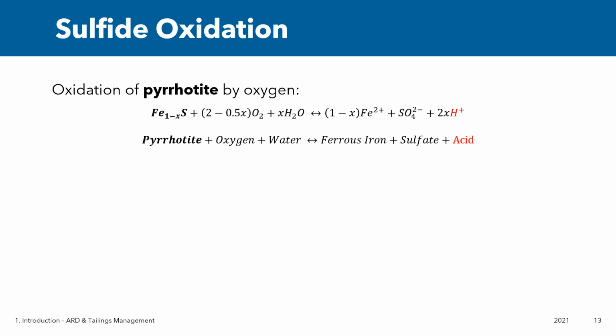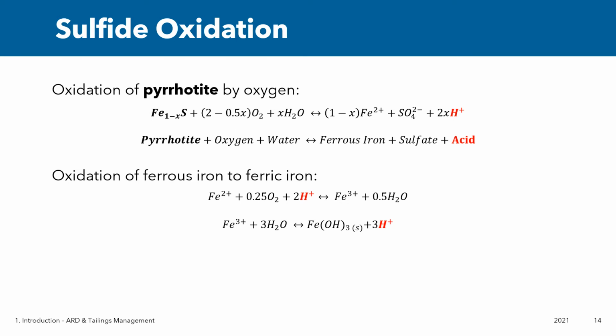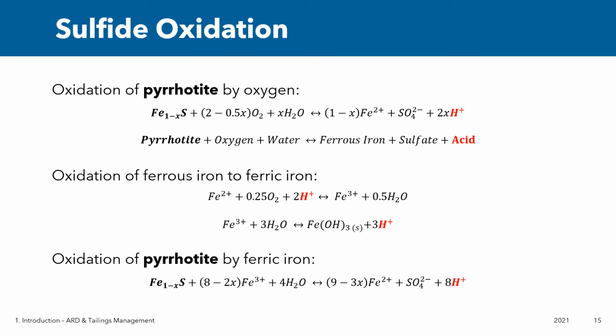ARD occurs when sulfide minerals are exposed to oxygen and water, and they react to produce cations, sulfate, and acid. For pyrrhotite, as shown here, oxidation by oxygen occurs when the minerals are in contact with the atmosphere. As that reaction occurs, ferrous iron is released into solution, and those ions can subsequently be oxidized to produce ferric iron. The ferric iron ions can then either react with water to form an iron oxyhydroxide, which can potentially sequester harmful metals, or the ferric iron can further oxidize pyrrhotite, resulting in substantial acid production. So the initial three reactants, the pyrrhotite, oxygen, and water, are the components that need to be managed.